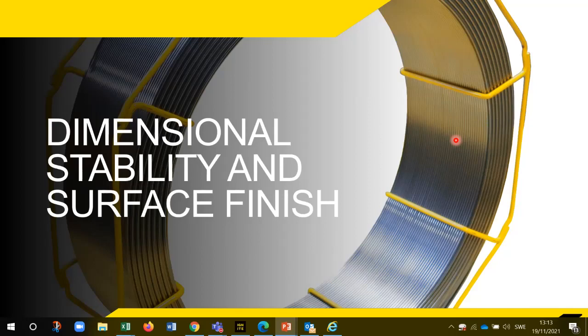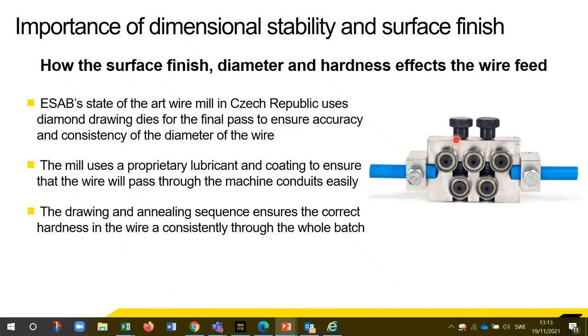So talking about mechanical dimensions, stability, surface finish. So how the surface finish affects the wire feed. Now, ESAB's got a state-of-the-art wire mill in the Czech Republic, and the consistency is ensured by virtue of us drawing the last diameters drawn through diamond dies. So these are very, very stable, very hard, last a long time. So you know that at the beginning of the spool, the diameter is going to be the same at the end of the spool to within 0.0001 millimeter.